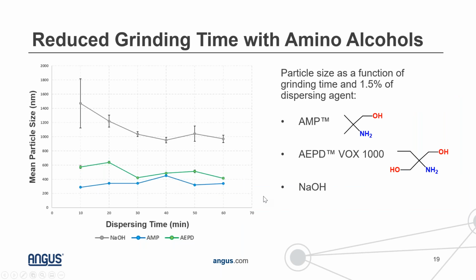So this can also help you from a practical standpoint, because it can help reduce grinding time. This is a graph that looks at the dispersing time versus the average particle size. What we find is that if we're using sodium hydroxide as a neutralizer in this grind, there's a general slope downward as the particle size decreases with time, which is what you would expect. After about 40 minutes or so, that's when you really achieve your minimum particle size from that grind. But if you run this dispersant grind with either AMP or AEPD, you're essentially getting your minimum particle size after only 10 minutes, which is significantly less time than with sodium hydroxide as a neutralizer.